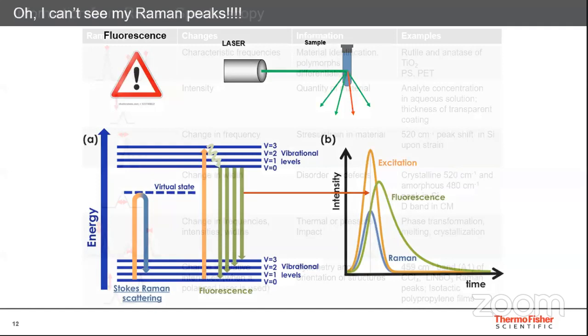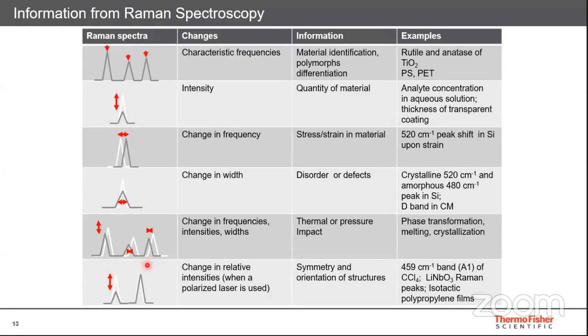Well, what kind of information do you get from Raman? Now, as I said, Raman spectroscopy, similar to IR spectroscopy, can be used for molecular identification as well as quantification. But Raman gives you something more. Raman can be used for polymorph identification, which is one of the important applications of Raman. For example, TiO2 exists in rutile as well as anatase form, and it shows different frequencies for rutile and anatase. So from the characteristic frequency that you see in Raman spectra, you can identify the material as well as what kind of polymorph of that material is present. From the intensity of the peak, you can understand the quantity of the material. That means you can do quantification of your material using Raman spectroscopy as well.